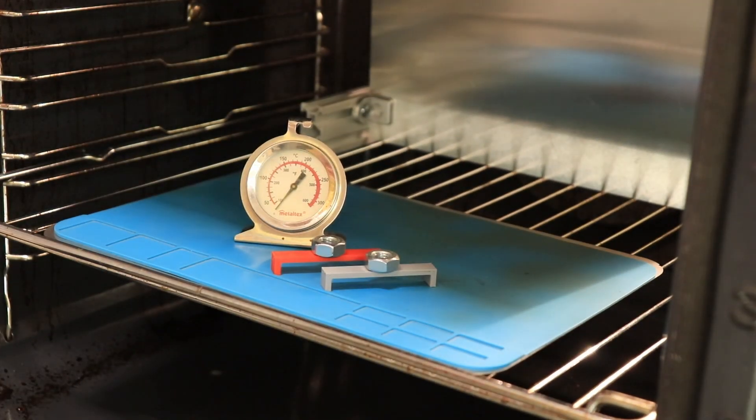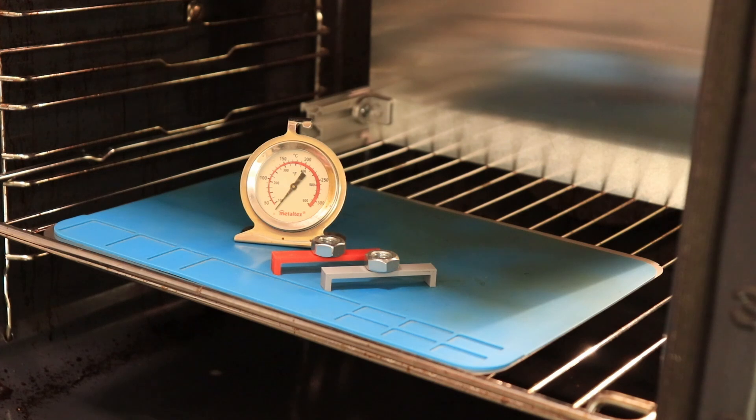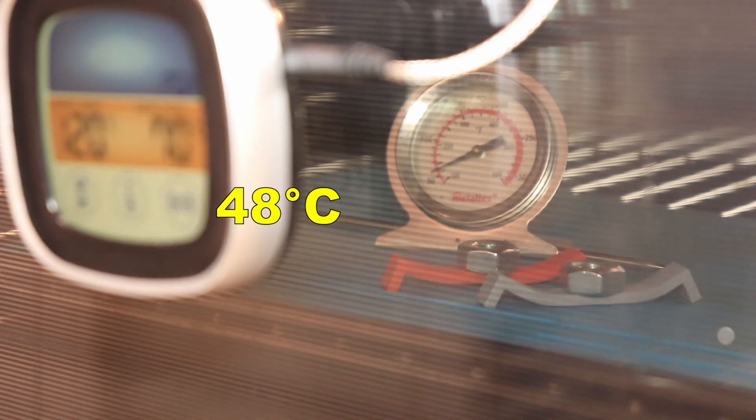The temperature test with the M10 nut is a small load and properly PLA will start to deform at approximately 50 degrees Celsius. I'm curious which one will start to deform first. This is 25 times speed up video and you'll see soon both materials start to deform at the same temperature, and that's 48 degrees Celsius in this case. This is typical for average PLA.